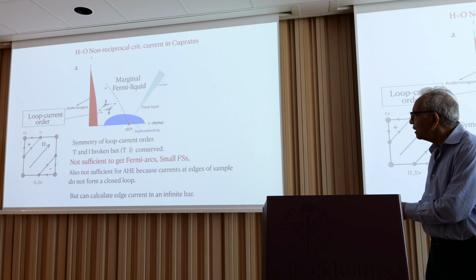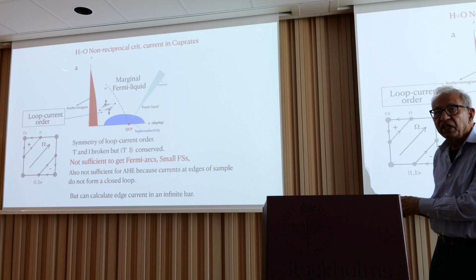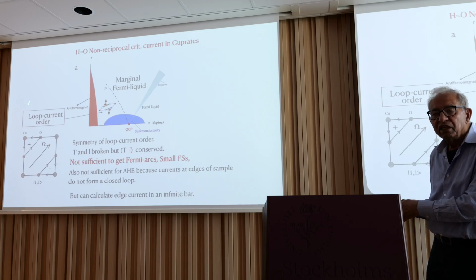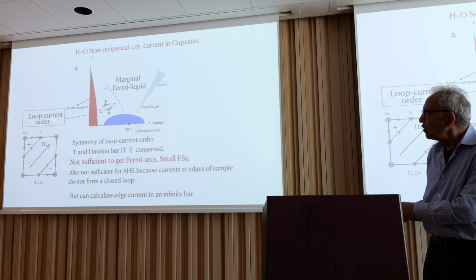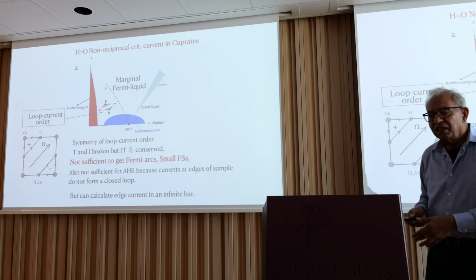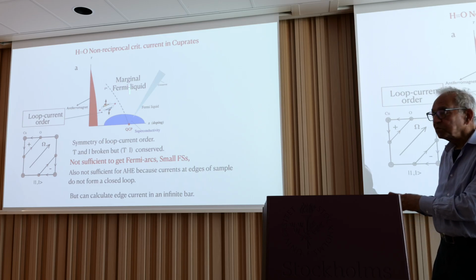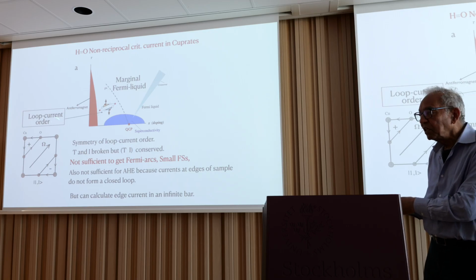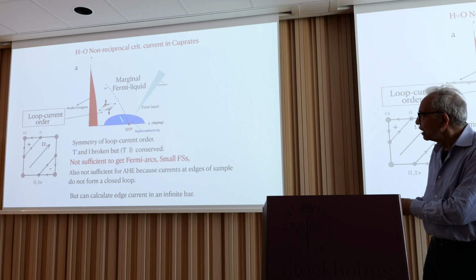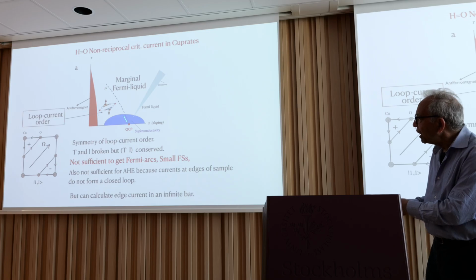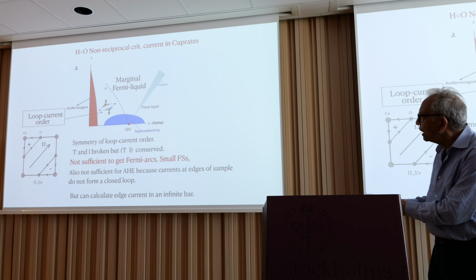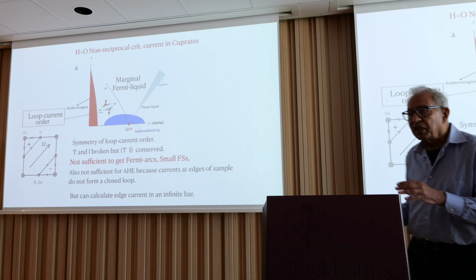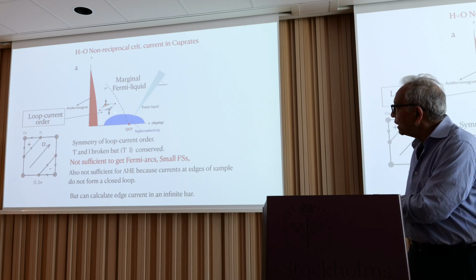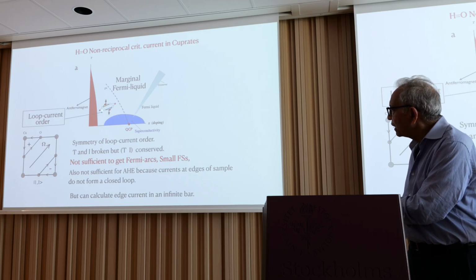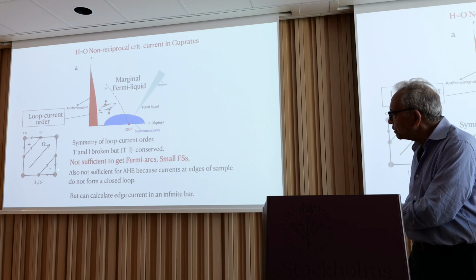The most famous of them is resistivity, but almost anything you study, nuclear relaxation rate, Raman scattering, optical conductivity, they're all peculiar. And with a bunch of colleagues, I suggested that that can only happen if there is a singularity at zero temperature in certain response functions. So that posited a quantum critical point, with the hypothesis that the imaginary part of the fluctuation spectra goes as omega over T, or the real part goes logarithmically with temperature. That required one to understand that there be a transition of some kind across this line, which had to have some rather remarkable symmetries, and I proposed that there can be loop current orders in this regime, and this particular symmetry was proposed.